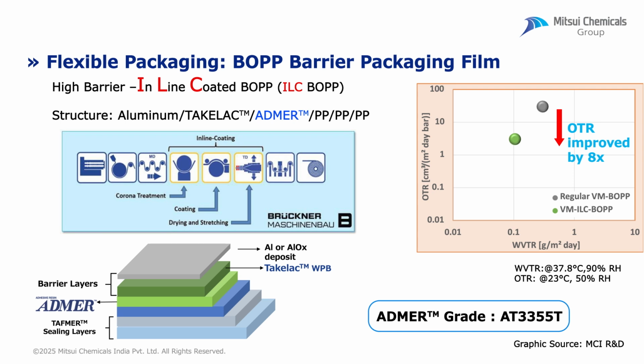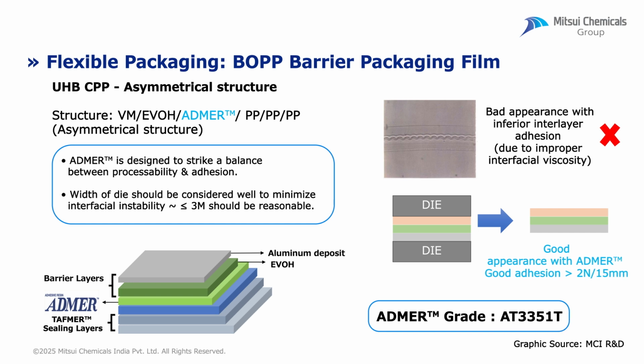Admer sustains high stretching and gives excellent adhesion with coating during the inline coating process. This film is suitable for barrier requirements in products like cookies flow wrap and chips pillow pouch. Similar to BOPP, Admer is also used for asymmetrical CPP barrier film, where it provides excellent adhesion to polyamide and EVOH